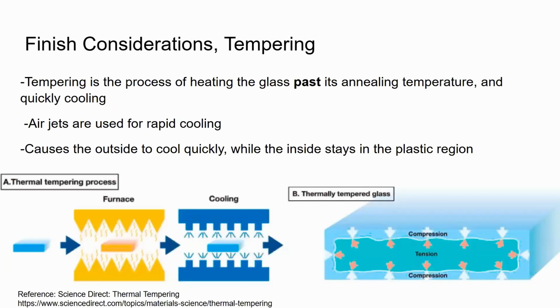A further thing that you can do to glass is tempering. Instead of just making it smooth like annealing, you heat it up past its annealing temperature and then you cool it very fast instead of slowly. You cool it with air jets. Usually, when they make annealed or tempered glass, they roll the glass over some rollers where it heats up in an oven. Then in another room, it passes through, like right here, where the air jets spray cold air at it rapidly. This allows the outside to cool much faster than the inside of the glass, so it hardens on the outside before the inside hardens.